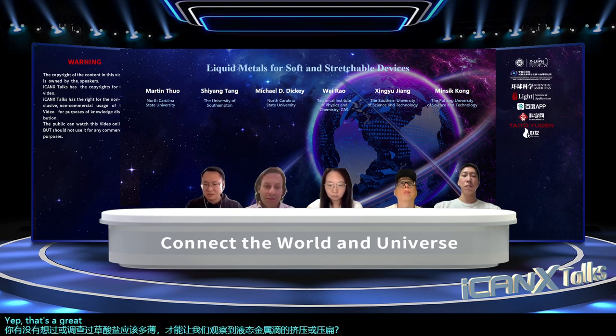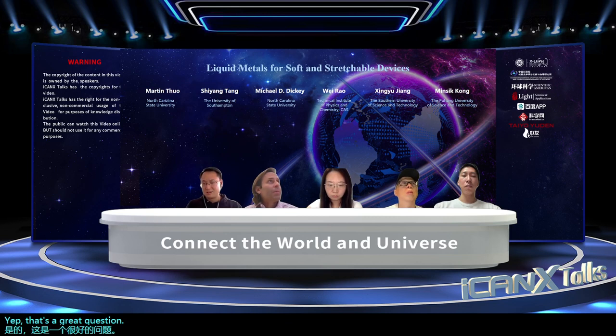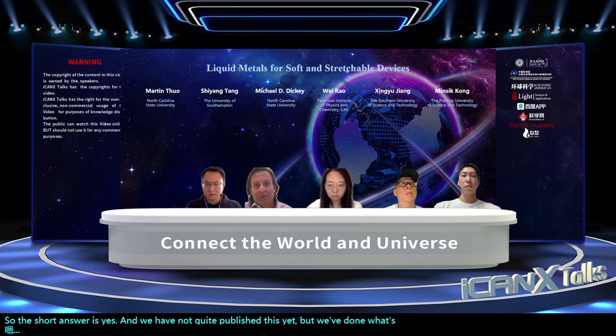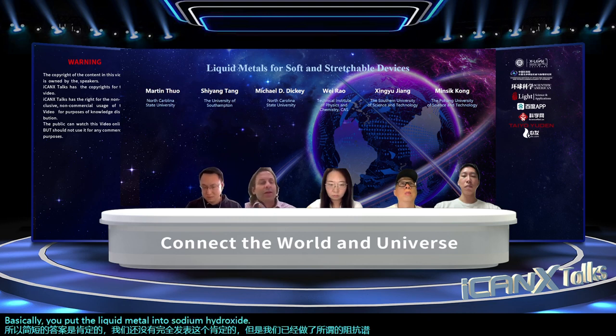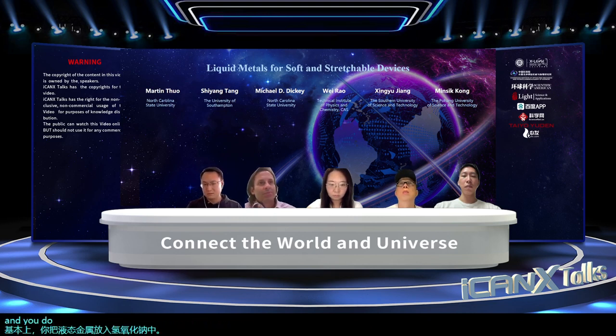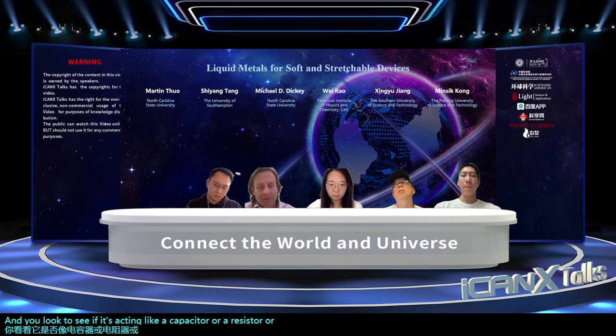Yep, that's a great question. So the short answer is yes, and we have not quite published this yet, but we've done what's called impedance spectroscopy, which is basically you put the liquid metal into sodium hydroxide, and you apply frequencies. You sweep a frequency with a very small voltage, like 10 millivolts or something like that. And then you look at the response. And you look to see if it's acting like a capacitor or a resistor, or basically you're looking at the relationship between voltage and current.